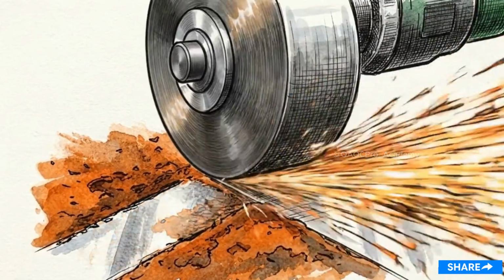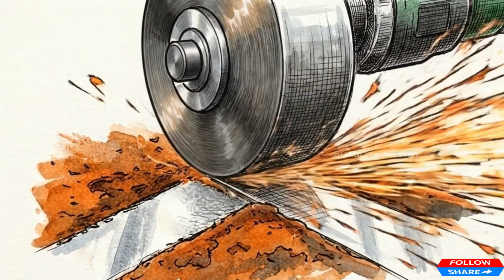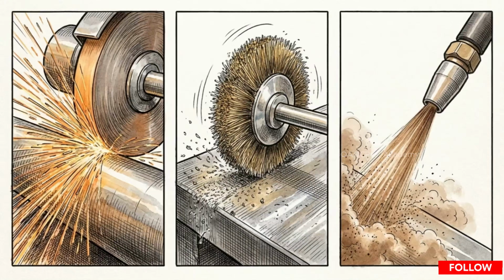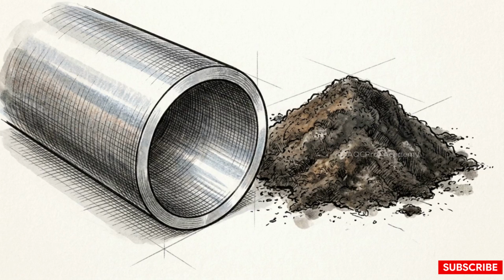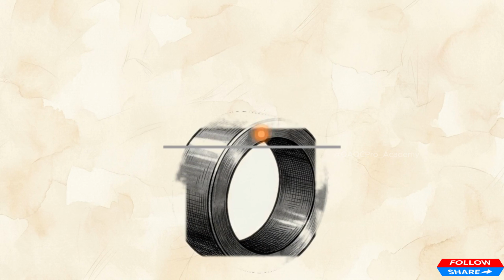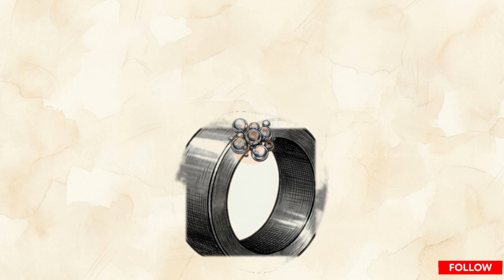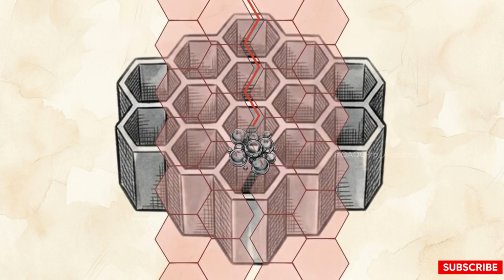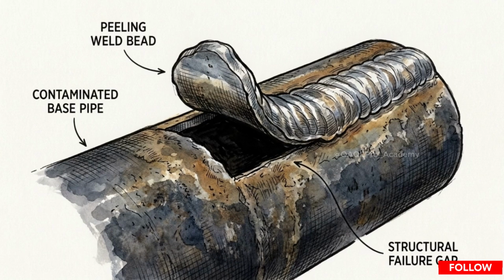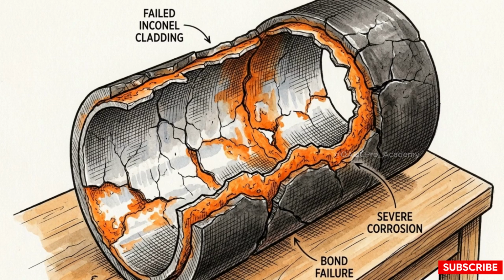You must strip the carbon steel surface down to bare, shiny metal before any welding begins. Achieve this by grinding, wire brushing, or sandblasting. The goal is the total removal of all mill-scale, rust, and surface oil. When working with galvanized steel, you face the additional threat of liquid embrittlement caused by residual zinc. If zinc remains on the surface, the intense heat of the weld burns it into the steel grain boundaries, causing immediate microcracks that can compromise the entire structure. Even a microscopic layer of dirt or zinc will ruin the bond of the Inconel overlay, making the cladding project a failure before it truly starts.